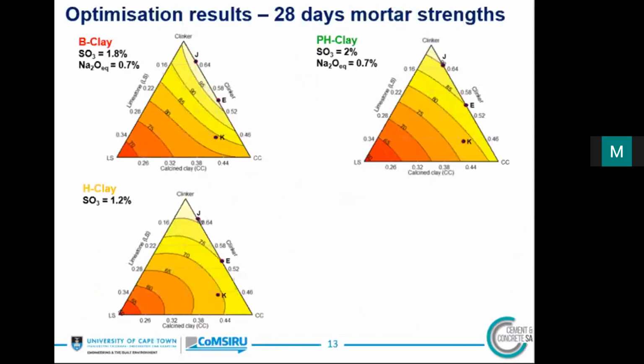Now the next task was to get optimal proportions of these materials. Here, the compressive strength of mortar was used as the performance measure for optimization. And LC3 mixes with clinker levels between 40 and 70% were obtained using what's called the mixture design 3 factors approach. In this approach, the simplex shape is a triangle, and it's possible to come up with contour lines within the triangular regions, as you can see here in these diagrams, and to estimate proportions that will give best performance.